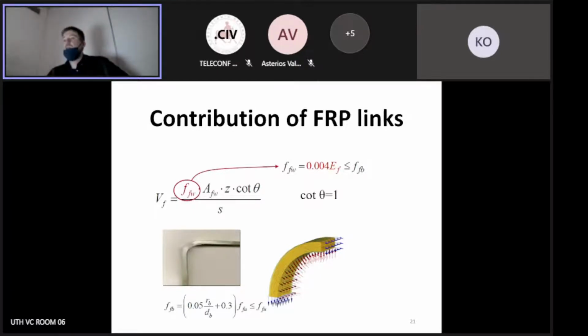Of course, we have to remember also that there is one issue with the FRP shear links. As I said, the transverse stiffness is much lower than the longitudinal stiffness along the fibers. So there is a risk of a premature failure in the corners adjacent to the longitudinal reinforcement. So we need to also account for that and reduce this stress to the allowable stress in the shear links using this equation.